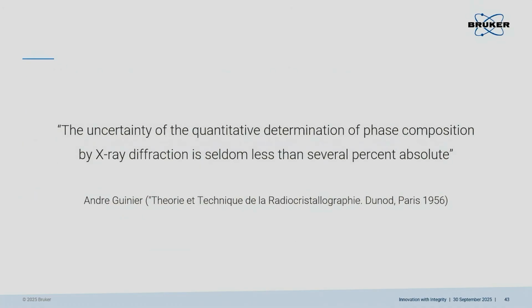And that is my final slide with a citation by the famous Andre Guinier. And nothing has changed. That is my take-home message in the past 70 years. So we have the tools to become much more accurate. Often it is difficult, often it's not needed. But in essence, even though there are many examples where we can show that we can do quant with an accuracy of better than 1%, you will be in a range of several percent absolute, 8%, not better.